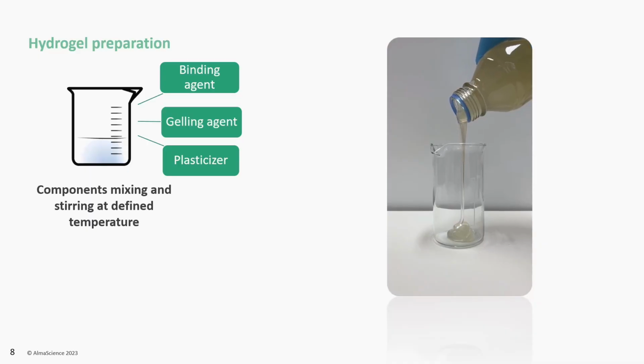To prepare the hydrogel is very simple. We just mix the components at the defined temperature. This is one of the resulting formulations. As you can see, hydrogels are very thick, so they have very high viscosities, which kind of limits the amount of solids we can go with in these solutions.